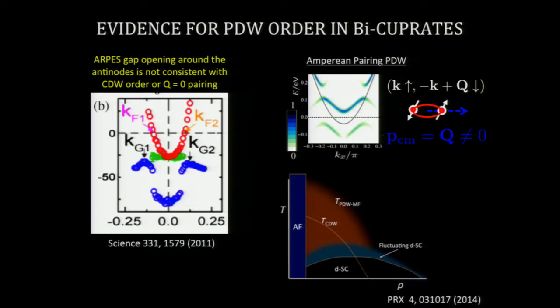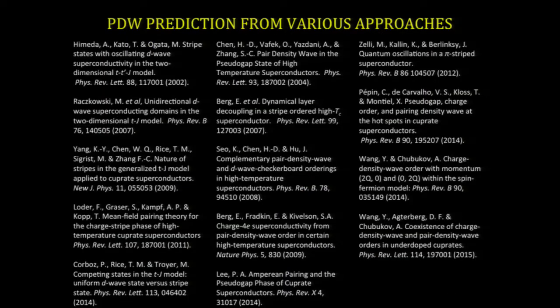So here you have this pair density wave which is incoherent. There's no phase associated yet. There's just Cooper pairs that are trying to bind. They're kind of modulating, but there's no phase stiffness to the system. You get down, you get the charge density wave, and eventually you get down to d-wave superconductivity. And along that, there's a whole slew of other proposals for the fact that there could be a pair density wave in these systems. So how would you actually really check for a pair density wave?